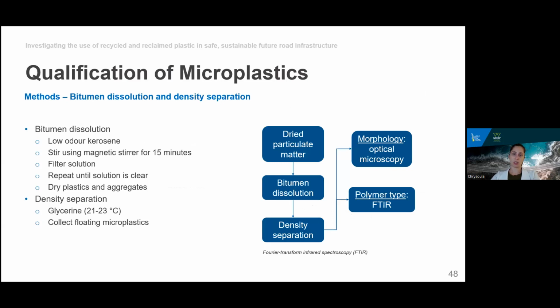So the way in which microplastics affect the environment has not yet been conclusively defined. Therefore, even though their quantification was important, it was thought that finding methods for their qualification was also necessary. In this method, we took the dried abraded matter, dissolved the bitumen using low-odor kerosene, using magnetic stirring, and filtering the solution until clear. Then we used glycerin to separate the aggregates from the microplastics via density separation. Finally, the floating microplastics were collected using a pipette.